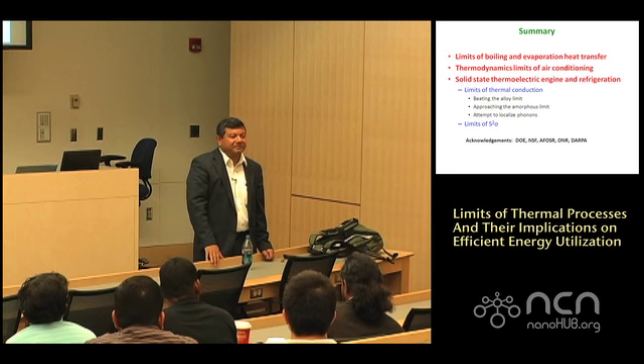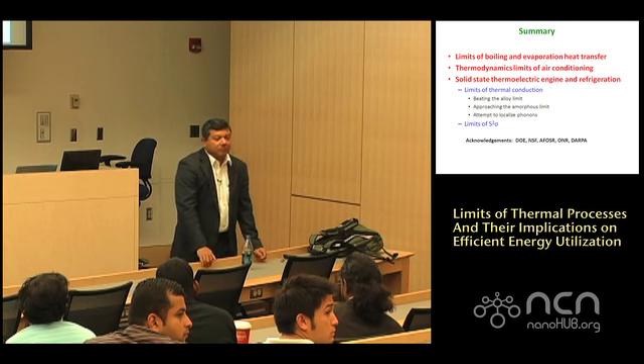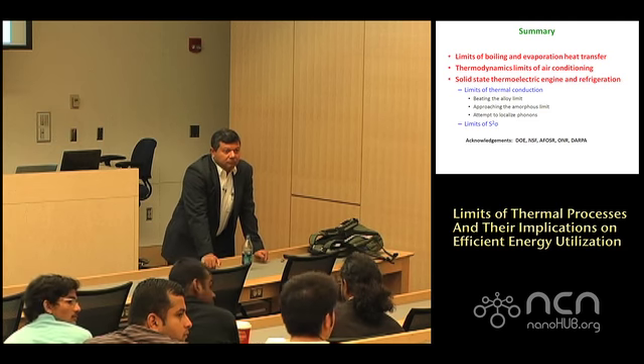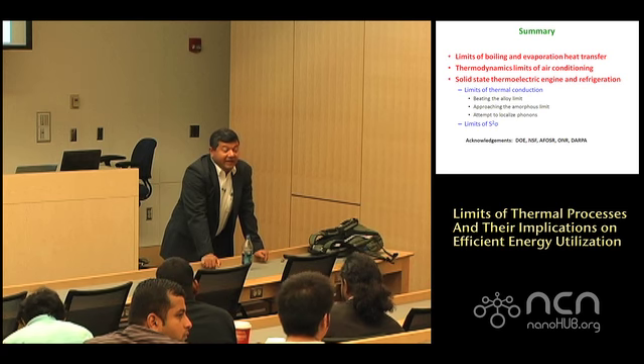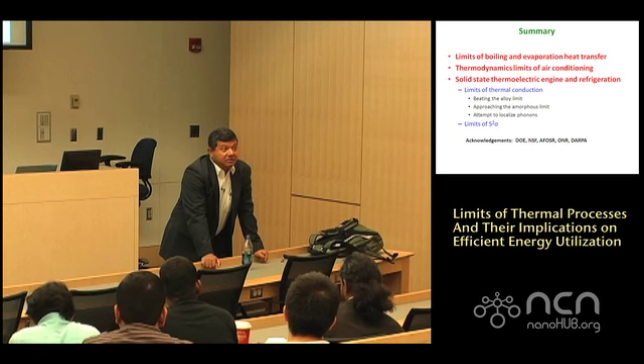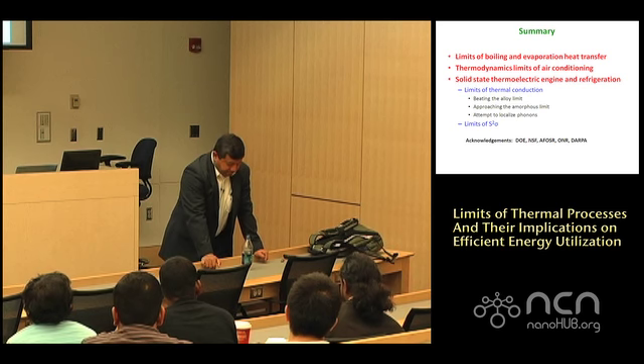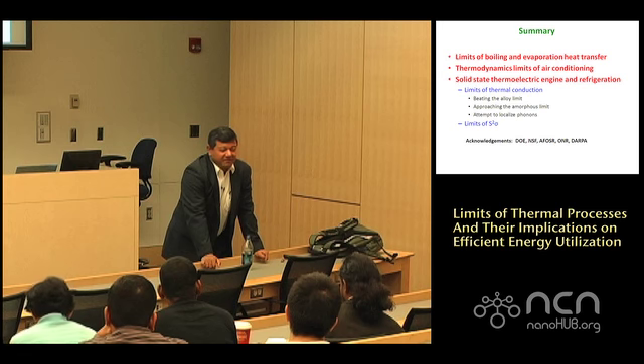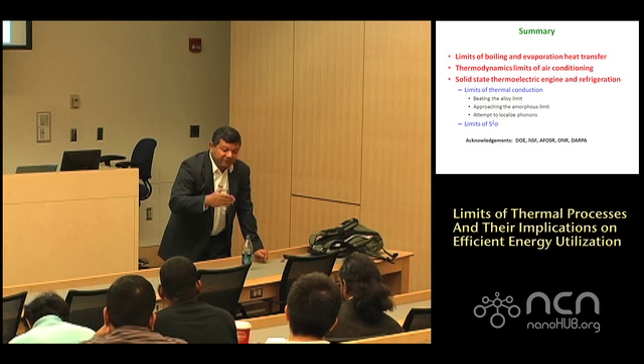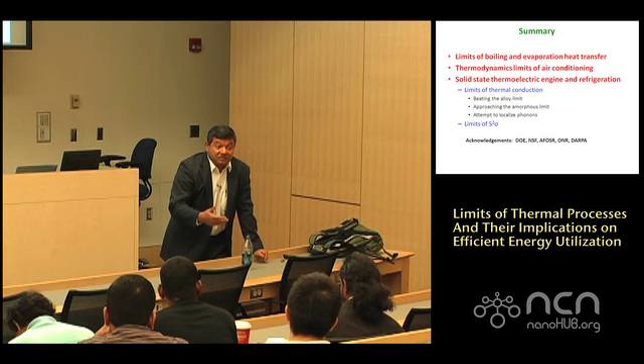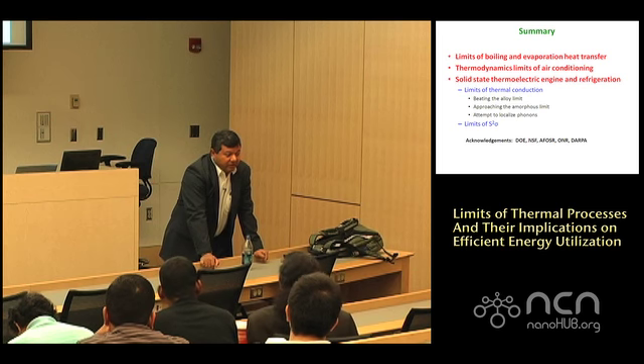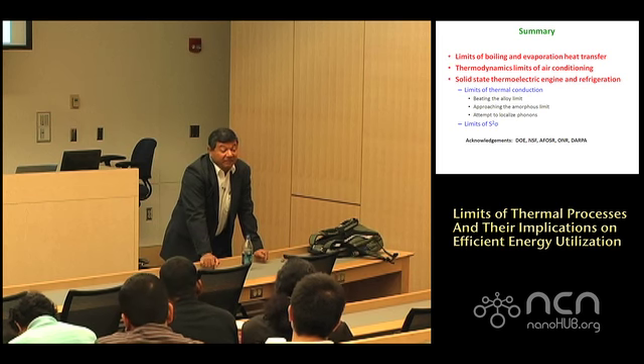Yep. So based on your experience with thermoelectricity, especially power factor, is it superlattice or bulk? What is the way to go in future? I don't see any reason to go to superlattice, really, frankly. Well, I shouldn't say that. People expected that when you go to a superlattice, you'll get band gaps and everything. It hasn't really been true. No one has really seen band gaps except in a very few experiments, and no one quite understands, because even if you have a sharp interface, it's not quite sharp, there's roughness, so coherence is lost. So the thermal conductivity is basically a function of interface density. That's it. There is no coherent effect. So if you can make interfaces very close, maybe that's the way to go.